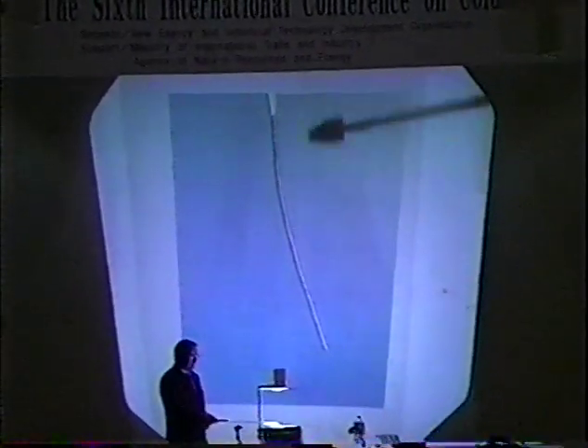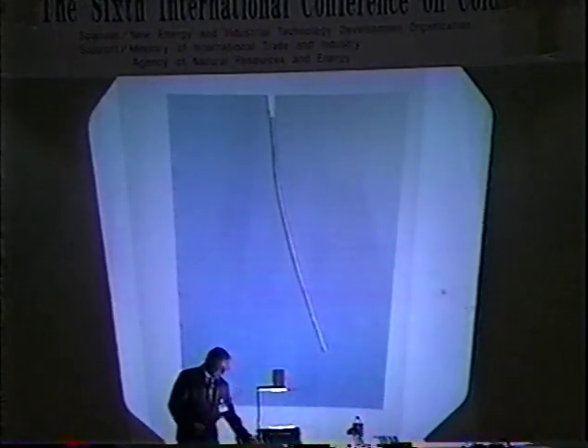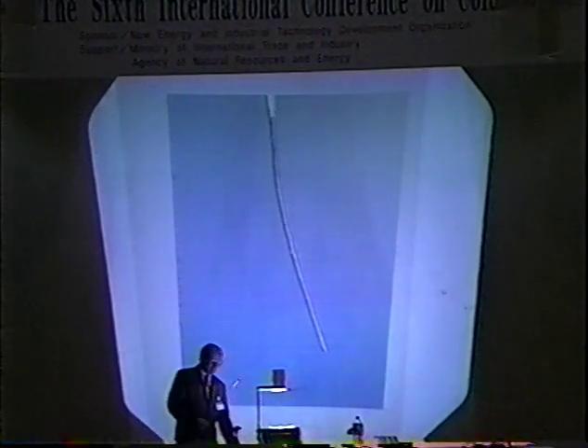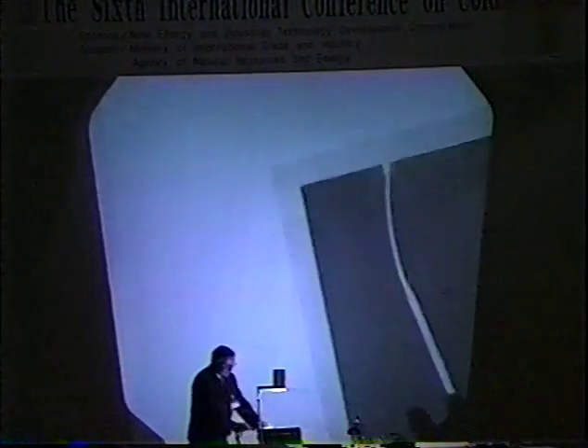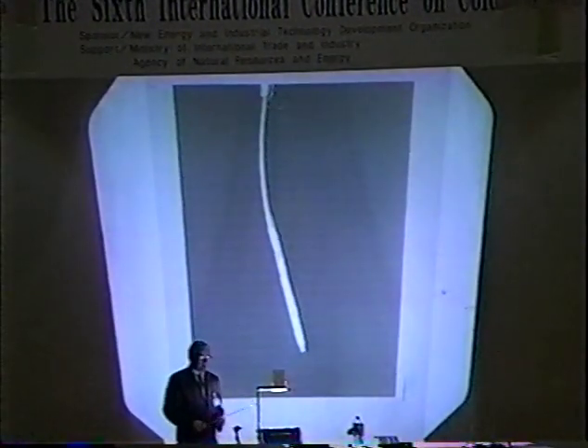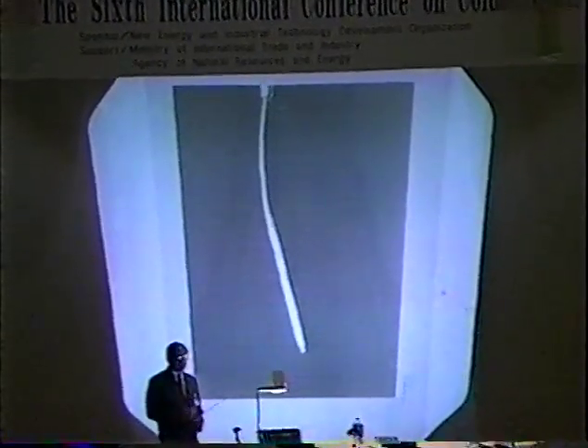I should point out that we're now using very, very high purity D2O. We're using very high purity solvent and electrolytes, and we're using quartz instead of silicate. You can see that after 160 days of electrolysis, there are no heavy black deposits of materials that have been leached out of the silicon present on these electrodes. Previously, these electrodes were laden with very large amounts of black deposit, as we all know. When the thing boils dry, you have violent boiling, and you cannot control the cell. You can see some of the white deposit of the electrolyte left, and that's all. Sorry, we are running out of time, so still one question from someone.